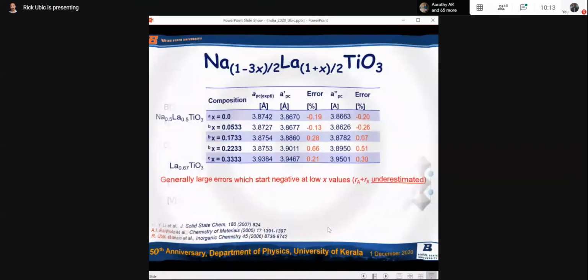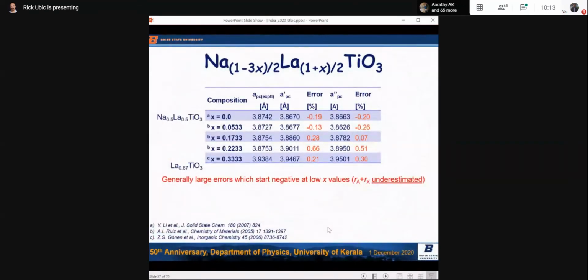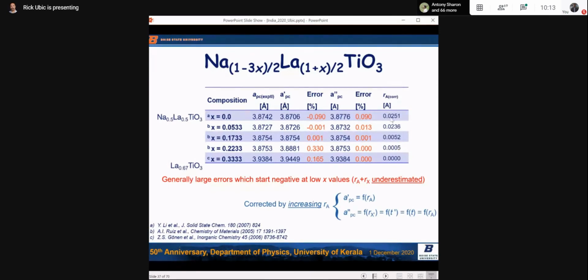But the problem was still with the ordering, right? So we look at this again. Here's our several compositions of sodium lanthanum titanate. X equals 0 is the one-to-one perfect order, and then we deviate from that. Here's our lattice constants, right? A prime, A double prime. Our errors, again, these errors, they don't look huge in themselves, but they do start off largely negative and become more and more positive as you go on. That is the telltale sign of an underestimation of the AX bond length. So we correct this, again, with A site corrections, positive, so we're expanding the A sites this time. And we get our errors to go away.